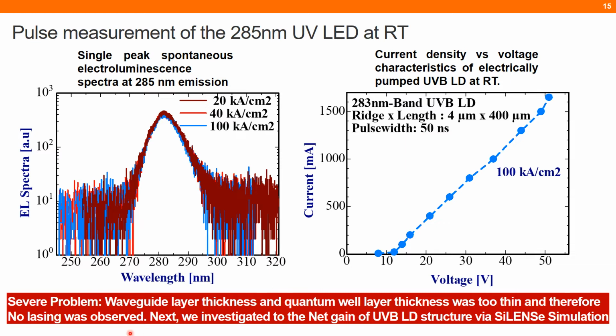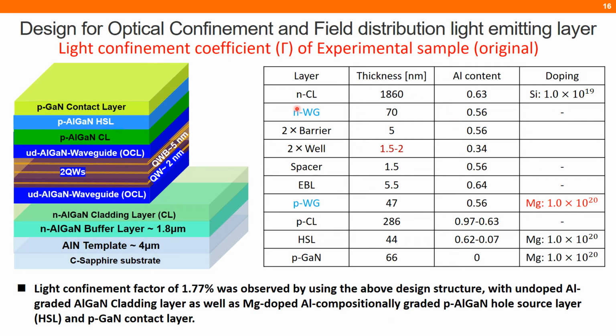So in this case, we have the problem with the waveguide layer thickness. I will just briefly mention, because we could not get lasing, but we got some abnormal oscillation that we will report later. So anyway, this is the device structure, which experimental device structure is given in this table. The thickness of the N waveguide and P waveguide was not optimized, so the light confinement factor of 1.77% was achieved for this. We also checked the P waveguide side with magnesium and without magnesium. So this is the overall scenario.